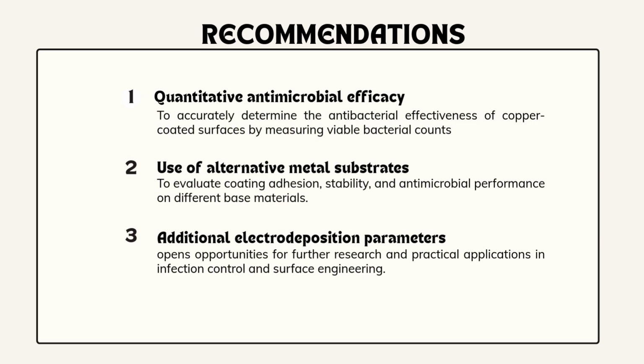For recommendations, future studies could use quantitative antimicrobial efficacy testing to accurately determine the antibacterial effectiveness of copper-coated surfaces by measuring viable bacterial counts. Secondly, to use alternative metal substrates to evaluate coating adhesion, stability, and antimicrobial performance on different base materials. And lastly, to use additional electrodeposition parameters to open opportunities for further research and practical applications in infection control and surface engineering.